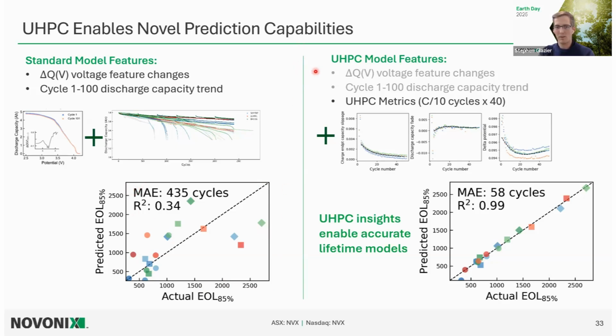What we did is we took those same features and layered in our UHPC metrics as additional features to train the models on. So these would be our coulombic efficiency, our capacity fade, our charge endpoint capacity slippage. So what we're now doing is taking some of the more kinetic-based implications of our testing and combining it with that really detailed electrochemical information about some of those rates of invisible reactions that you can't see with capacity fade data, and layering that in. And with all of those features layered in, the models perform much, much better.